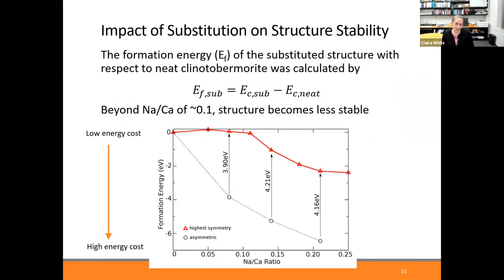What is shown on this slide is that result, and specifically this is the energy difference between not symmetric and symmetric for the distribution of the atoms. And what we show here as we go up on the x-axis is, with increasing sodium content of the crystal, what happens to the formation energy of the system, which you can think of as: is there an energy penalty to having sodium in some of the locations where calcium originally was in that interlayer region? And the answer is yes, there is an energy penalty, but it only manifests itself after a certain amount of sodium is incorporated into the structure.